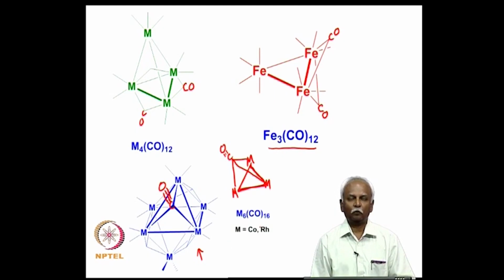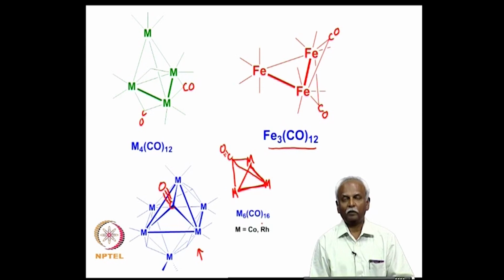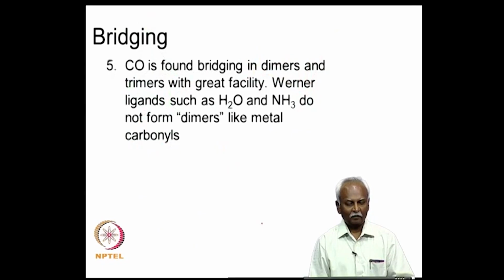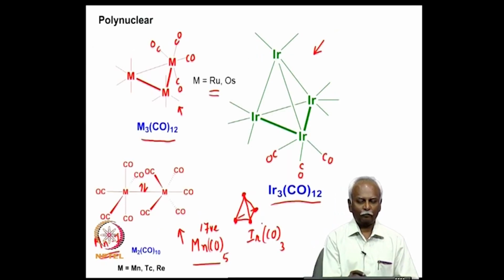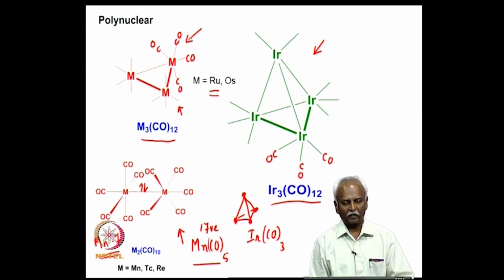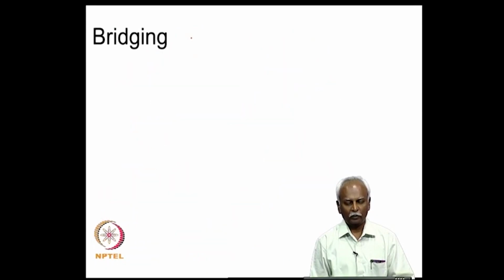So, this has raised a lot of debate as to the facility with which carbon monoxide can bridge and why it bridges 3d transition metals and not necessarily 4d and 5d elements. Both ruthenium and osmium do not form the bridge species, but instead we notice that they form only the trimeric species where you have no bridges, but terminal carbon monoxides. So, here you have all terminal carbon monoxides, and in the case of iron, you tend to form two bridges.